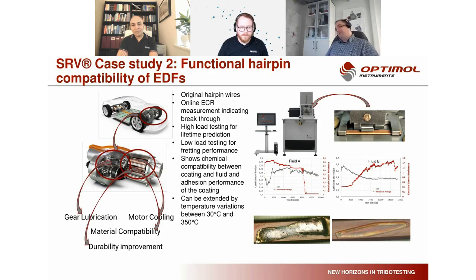Another up-to-date problem is the electric drivetrain, where we can test easily the compatibility of hairpin wires with EDF, the electric drivetrain fluid. Using the electrical resistance measurement, we can detect if there is a breakthrough of the layer, if there are damages, even after a longer time of test, and we can observe if the friction remains stable.